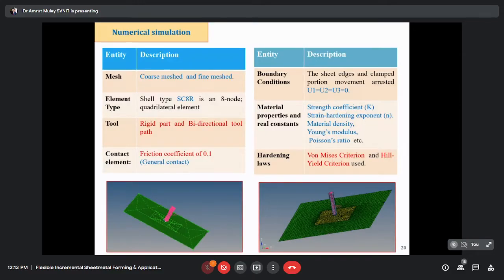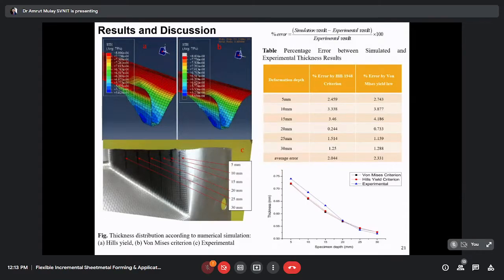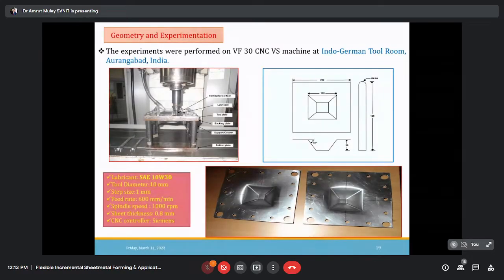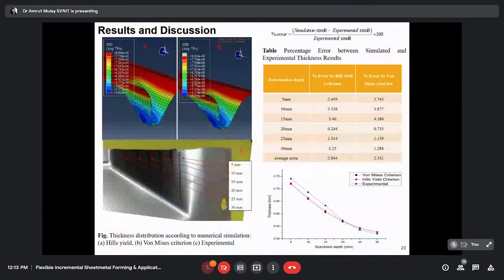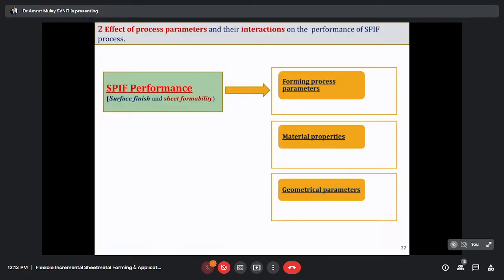Now we had the simulation, and after simulation we confirmed that anisotropy has some effect, but that effect is very small. The two criteria we used were Hill 1948 and Von Mises criteria. The same experiment with the same parameters we performed on the CNC machine, we took in the Abaqus simulation, and we found that the error difference is very low. Therefore we could conclude that anisotropy plays a very minimal role in aluminum alloys. So we proceeded with the parametric study, because we had already studied lubrication, which lubricant is best, and the effect of anisotropy, and then we performed our actual experiment.